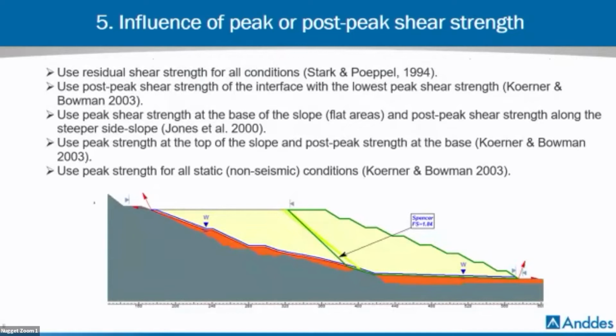The suggestions of different authors on the use of peak and post-peak shear strength in the design are summarized here, listed from the most to the least conservative. Starting with one author, who suggests the use of the residual shear strength for all conditions in the steps and in the flat of the leach pad. Then Koerner and Bowman suggest the use of the post-peak shear strength of the interface with the lowest peak shear strength of the two or three interfaces that we have. Another author suggests the use of the peak shear strength at the base of the slope and the post-peak shear strength along the steeper side.